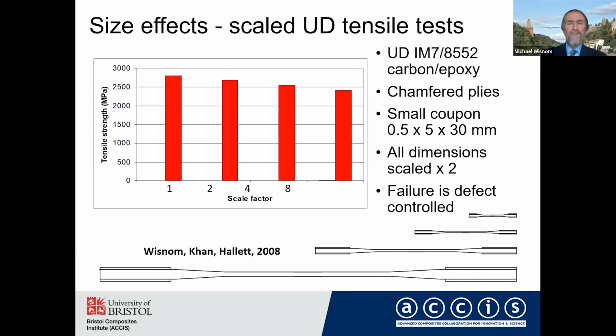So this is showing some results from some tests some years ago where we had UD IM7/8552 with chamfered plies, and we had some small coupons, and then we doubled up all the dimensions, the thickness, the width, and the length. So we go over a factor of 8 in terms of linear dimension, with a factor of 512 in volume. And you see that there is a significant reduction in the strength from about 2,800 megapascals for the smaller specimen down to about 2,400 megapascals for the largest.